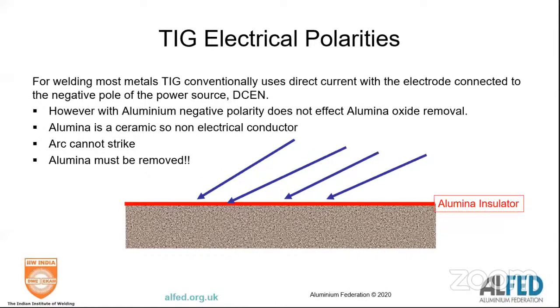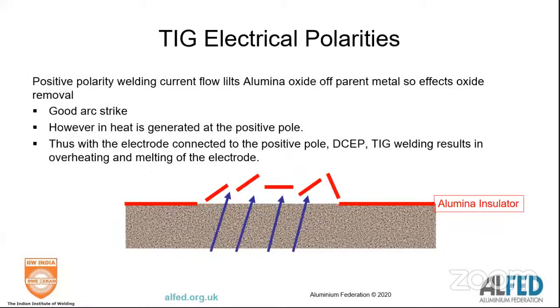With TIG, now you have a problem. The problem with TIG is that ideally you want to connect to the negative pole to keep the electrode cold, but that means that what you've got is an electrical insulator. So if you're going to negative weld TIG, and people do for speed, you have to either chemically remove it or grind it away, or alternatively plus pole weld it. And British Oxygen in the UK have developed a technique called plus pole welding, which they are using to weld aluminium at very high speeds.